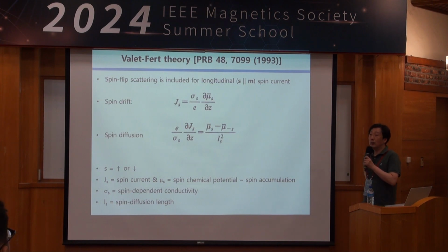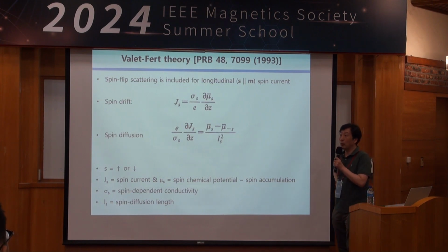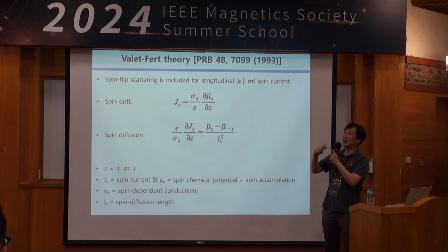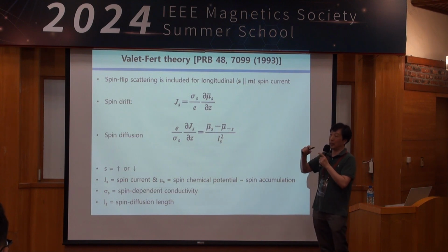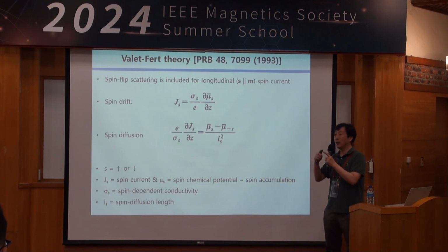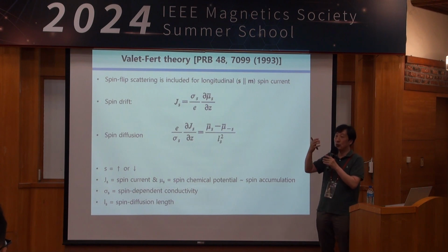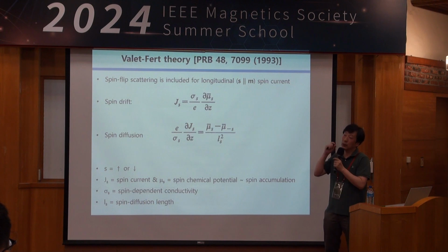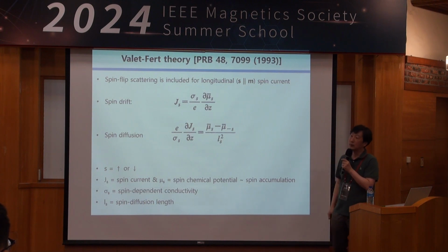Yeah, if you want to be very accurate, then you have to use the atomistic LLG equation. Even though DMI can make a canted magnetic moment, that magnitude actually changes during the dynamics. So if you don't use atomistic LLG, then you have to use a very crude approximation about that magnitude that would give an incorrect result. Okay, thanks.